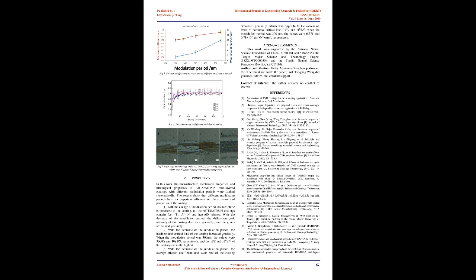Besides, when the modulation period is 300 nm, the grain size of the coating is minimum. Under the complex stress, the small-sized nanocrystals can slip or tilt slightly, which can buffer and release part of the stress at the interface, which is not conducive to crack initiation and film peeling, and is helpful to enhance the adhesion of the coating. At this time, the coating defects are less and the structure is compact, which is helpful to improve the critical load of the coating. On the whole, the adhesion of the coating is high, which is also the advantage of using arc-ion plating technology.